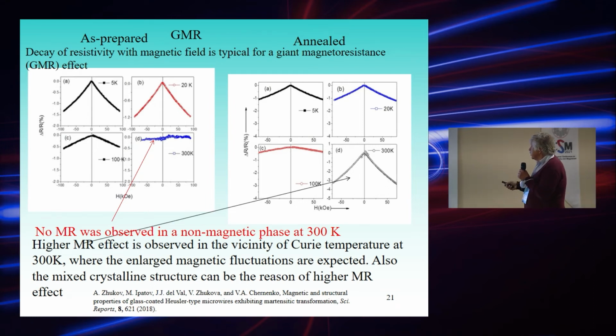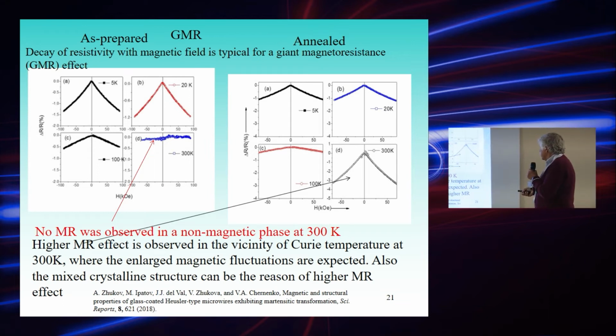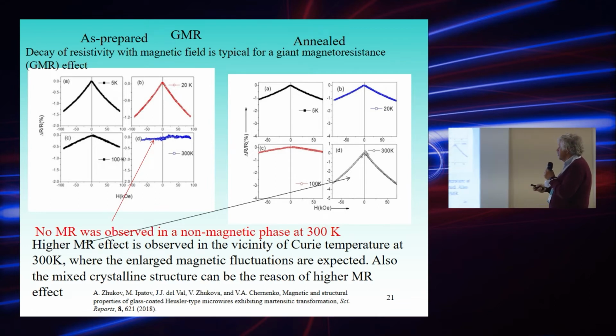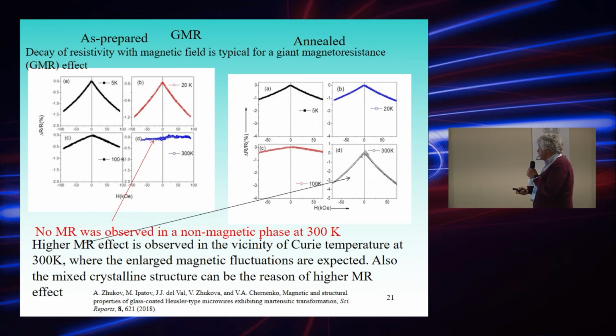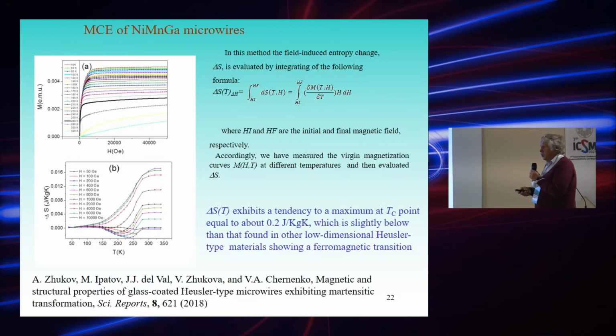Then in these materials we measured magnetoresistance, and these materials present magnetoresistance up to 2%. Of course, at room temperature the magnetoresistance was not observed because in this state the materials are already in the paramagnetic state. What was also interesting is that after annealing, magnetoresistance increased up to 3–4% near room temperature, probably because of the coexistence of two different magnetic phases in these materials near room temperature.